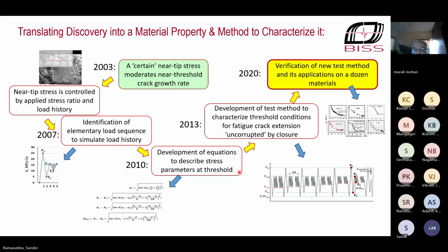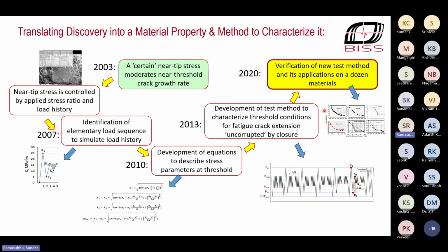Then the equations came up, and then a test method had to be developed to implement this in a reproducible way. So this is the load sequence that was used, and it is now part of the standard. And the first results were published in 2013. Between 2013 and 2020, we exercised this method on more than a dozen materials, published a lot of papers on them. They all showed highly reproducible relationships between threshold and near-tip residual stress. We even were able to show that non-heat treated additively manufactured material with residual stresses produced during the additive manufacturing had an impact on the plot. They just shifted the plot.